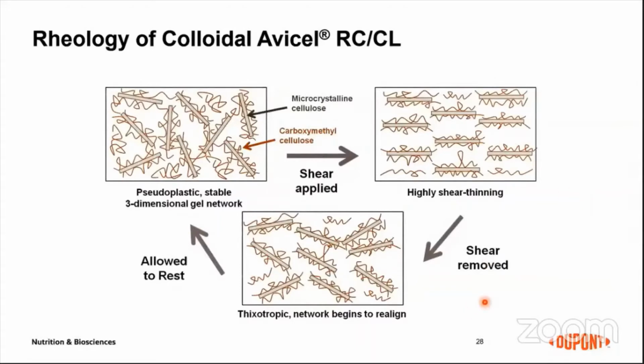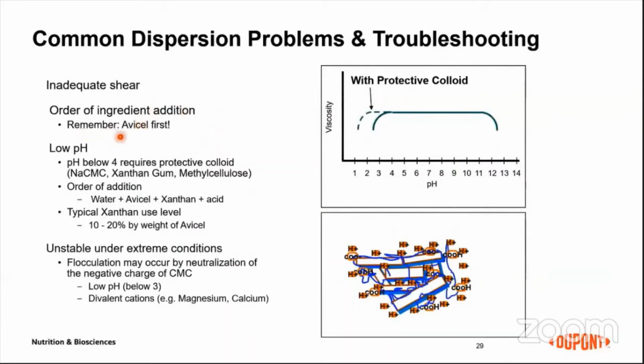So by shaking or applying shear force, you can decrease the viscosity of colloidal MCC suspension. But when you leave it in storage for a couple of hours or even longer, the 3D networks can be realigned, which means you can rebuild the 3D networks to exactly the same status as the beginning. So this is the mechanism of the unique shear thinning property of colloidal MCC suspension. Firstly, we recommend adding colloidal MCC first. For RC591, usually you need a high shear mixer to activate the colloidal MCC.